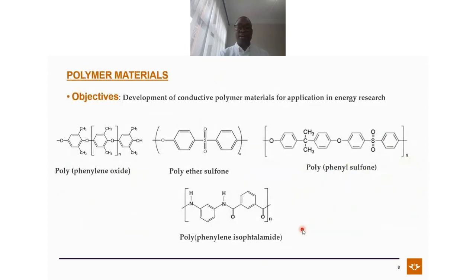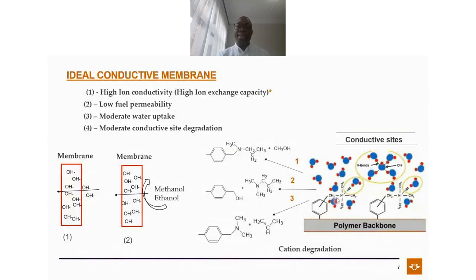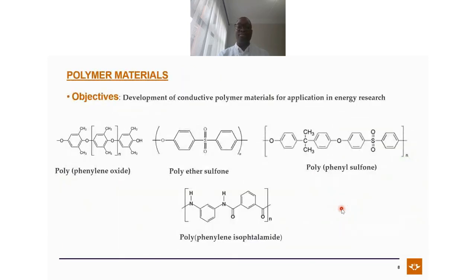As the Department of Chemical Science and the energy group, we are solely focusing on these 4 different types of membrane for our research. We're looking at polyphenylene oxide, we're looking at polyether sulfone, we're looking at polyphenylsulfone, we're also looking at polyphenylene isophthalamide. These membranes have high reaction rates. Remember, we want to take this material and add a conductive agent. So we want to functionalize this material. So the membranes that I use are supposed to have a high rate of functionalization, which these polymers have.